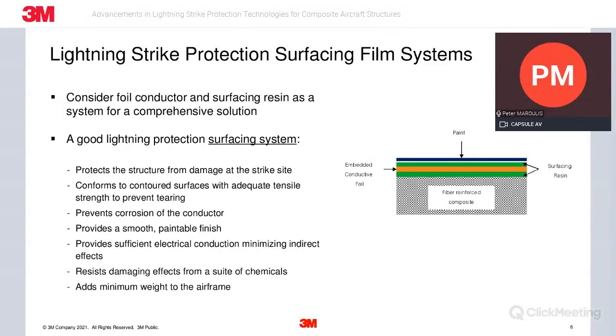So we really need to think about these foil solutions. When we look at traditional expanded copper foil configurations, it's basically a network of fibers that are joined together at nodes. You need to fill that with resin to get a smooth surface, which makes it important to think about it as a whole system. You see the image on the right there. You'll see in this presentation the combination of the resin and the conductor applied as the outer surface of the fiber reinforced composite, which will then see a paint process overcoated.